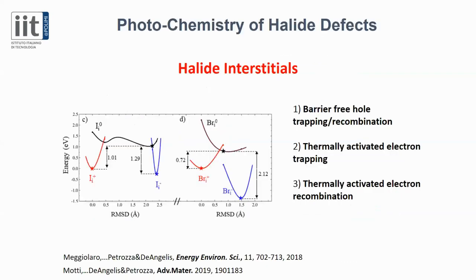What is the characteristic of these states? These halide interstitials are able to have an amphoteric character. What does it mean? So they can trap both electrons and holes. But what happens here, I'm showing on the left, the red curve, when they can trap an electron, they need to overcome an energy barrier to trap this electron. At molecular level, the defect needs to rearrange itself once the electron is trapped, and we have a kind of neutral state, which is this I0 species that I'm showing here, which is metastable.